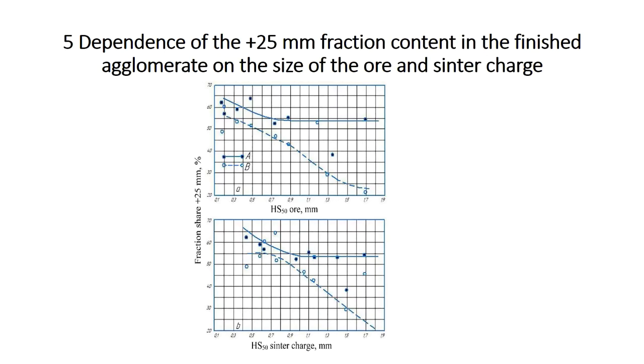index Hs50. With an increase in the size of hematite or B, a continuous decrease in the yield of the agglomerate fraction of plus 25 mm is observed, while for magnetite or A, starting with an Hs50 of 0.8 mm for a sinter batch of 1.0 mm, this value remains constant. In general, the yield of the plus 25 mm fraction in the agglomerate from magnetite ore is higher than from hematite, which indicates their different sintering capacity.